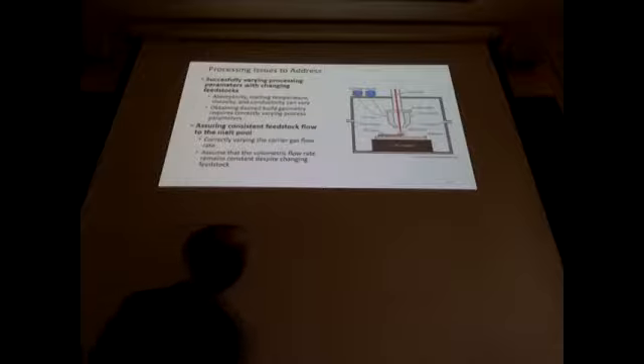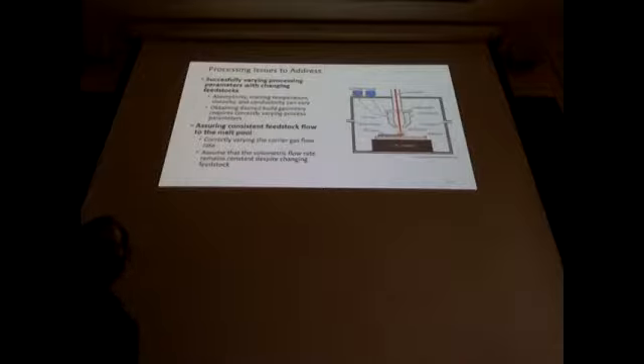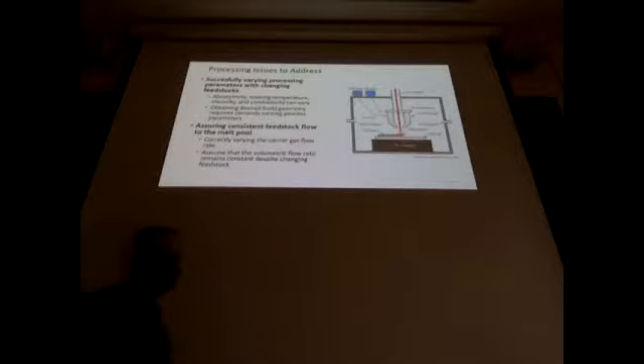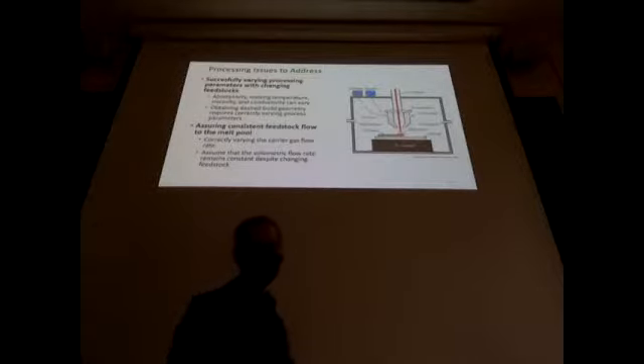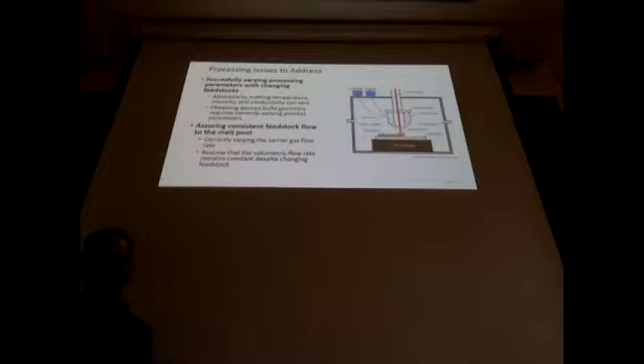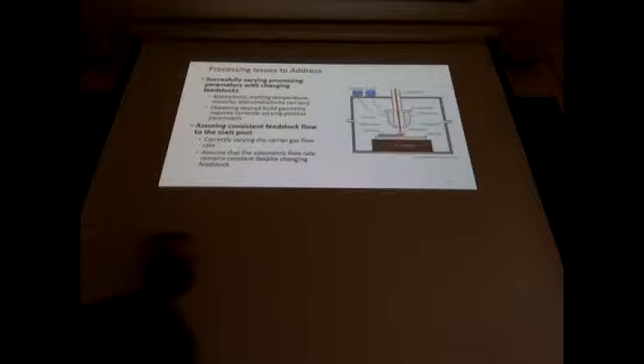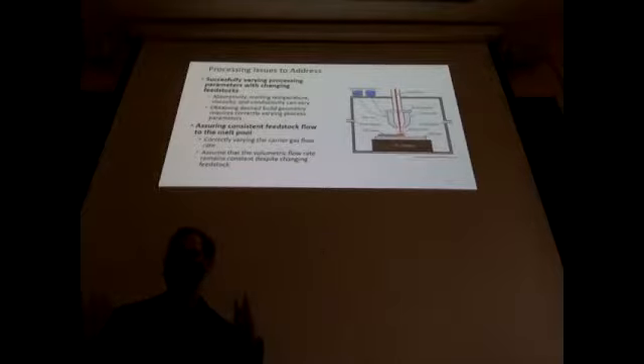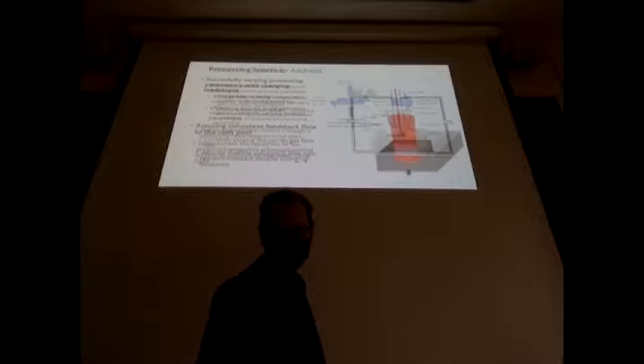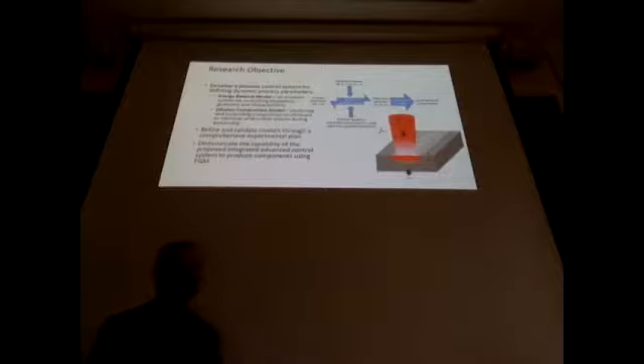And so we wanted to be able to successfully vary the processing conditions with that varying feedstock. The other thing we want to do is assure that we have consistent melt pool geometry as well. And again, that applies to, how do we make sure we feed it correctly to the melt pool with a varying powder? Can we always assume that we get the same volumetric flow rate of that material, despite changes in density from the feedstock to that melt pool? So that's kind of our research direction.